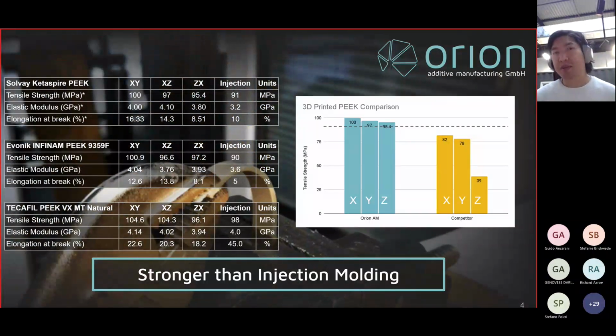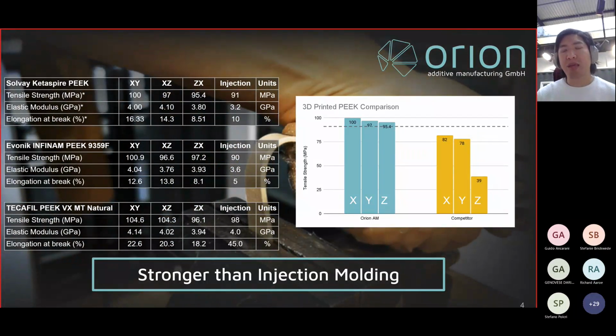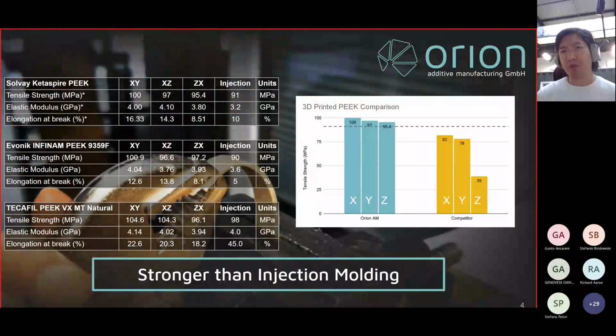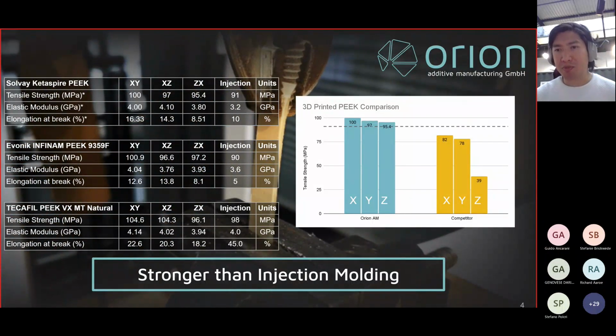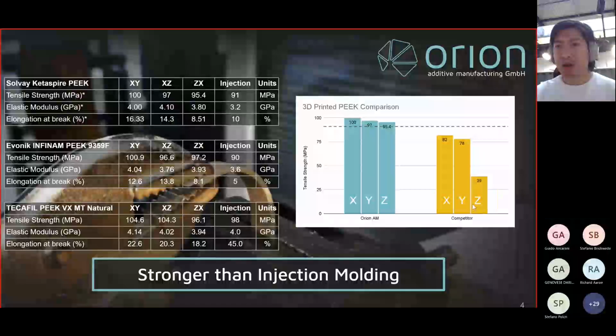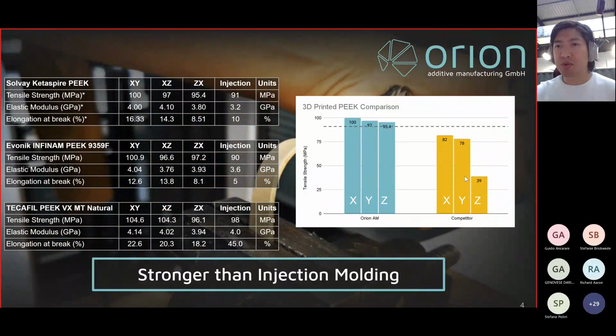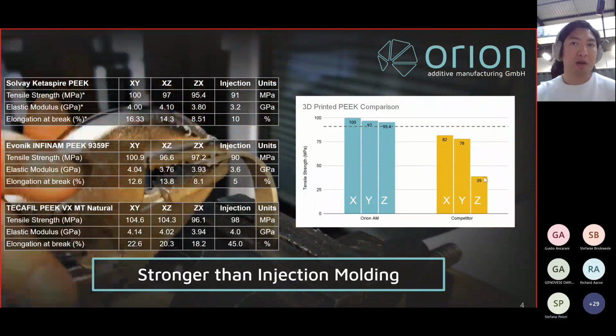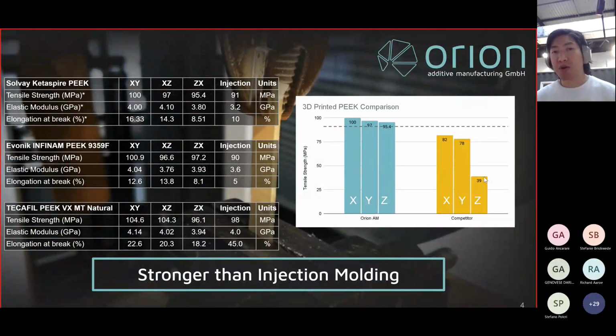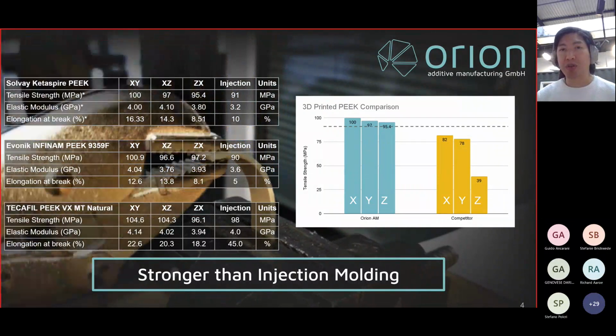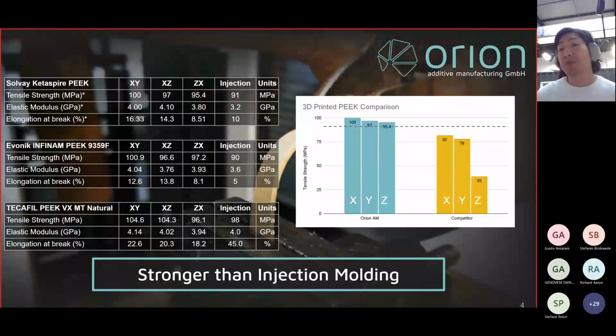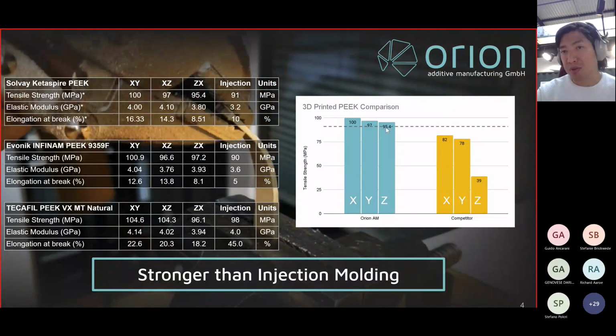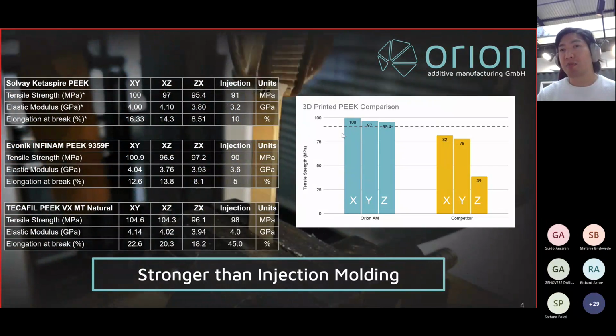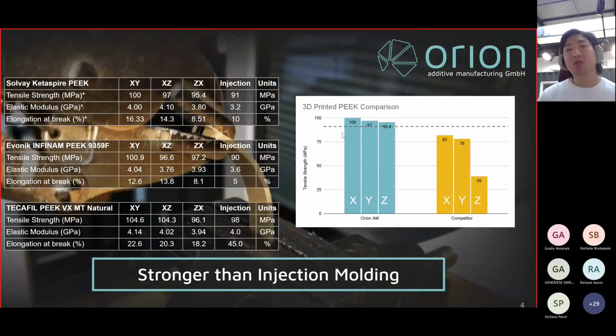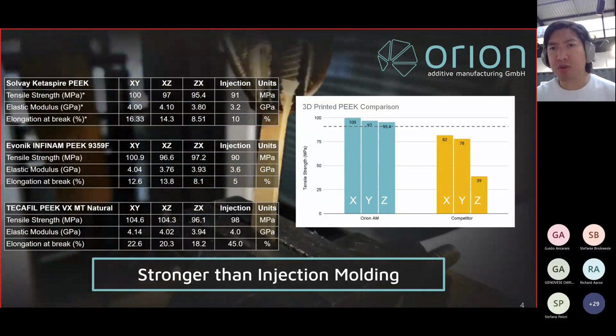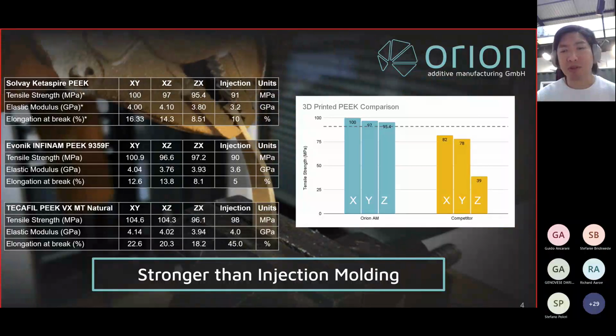So what this really means for us is that you no longer have to make compromises when it comes to additive manufacturing, especially with high-performance polymers. You don't have to think about what is the weakest link, because normally you would take your weakest orientation and say that is the maximum strength you can get out of this part, right? And then when it comes to certifying these parts or rolling them out into an end-use application, you have to take that into consideration. So it's a highly compromised part in that sense. But in our case, with our process at Orion Additive Manufacturing, you don't have any compromises. You can take a part that you used in an injection molding process or CNC machining process, and you can 3D print it without having any compromises at all.